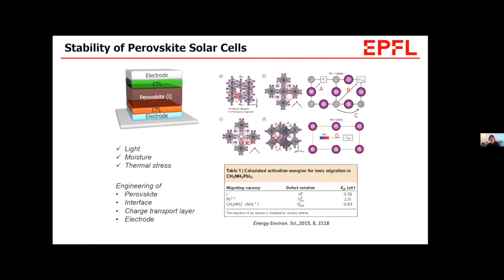I cannot judge by myself, but according to the literature so far, this mesoporous structure seems more stable in terms of stability. For example, it is known in general that planar heterojunction perovskite solar cells are more susceptible to ion migration. So probably the flattened interface matters, and there are several parameters that we have to consider. But so far I can say the mesoscopic structure is more stable than the planar structure cells.